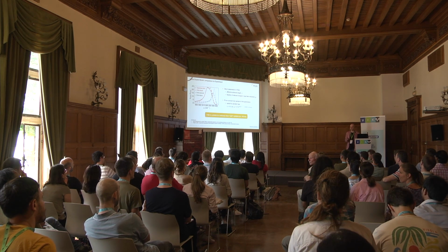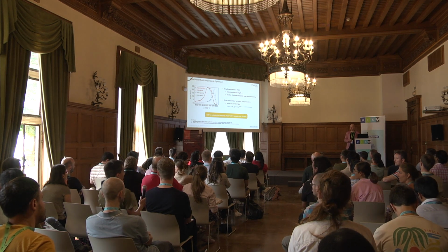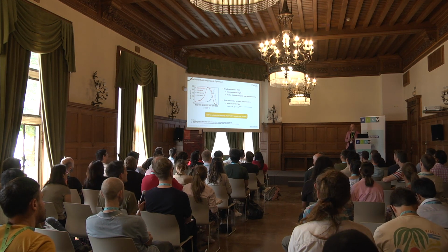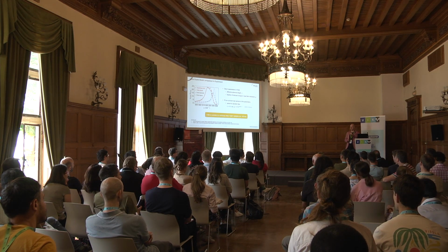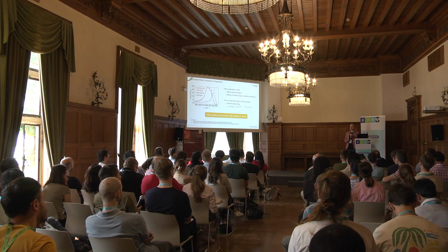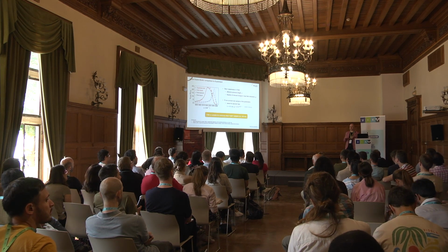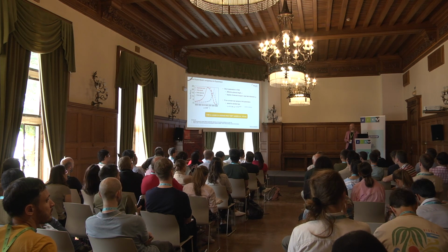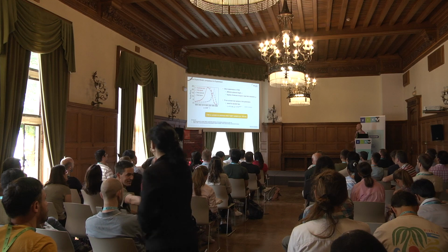Within the model, they're not fitted, they're calculated, so you can get analytical expressions. W1 is actually the focus, so that's the focal distance of the spheroid. W0, in the approximation, I think it's something like 1.38 times the radius of curvature. So the real fitting parameters, there's only two, these two, that's it.